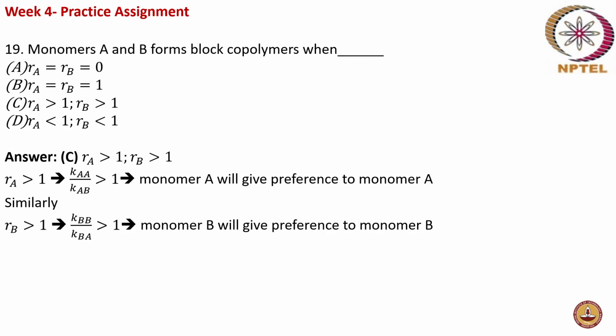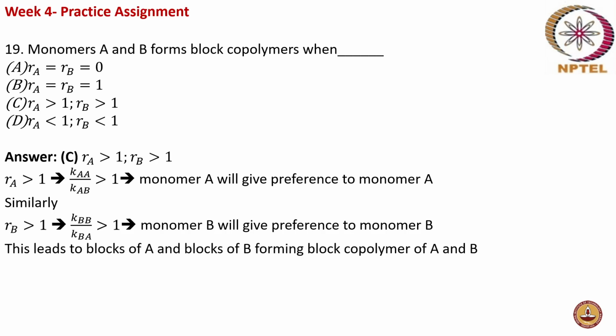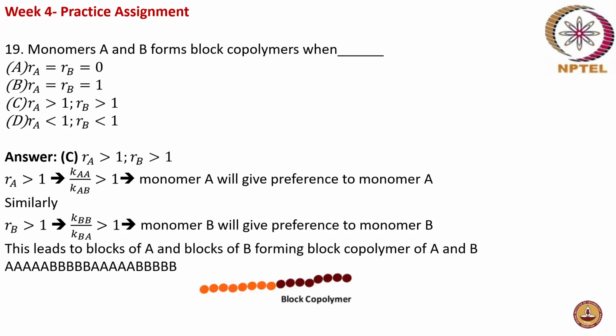And when will RA equal to RB be equal to 0? Then it will be alternating polymer, ma'am. Yes, that means A preferentially joins only with B and B preferentially joins with A, because your denominator should be higher. If the denominator value is very high, the fraction value tends to 0. That means you end up with the alternating copolymer. This is the explanation. The other case leads to a block copolymer of A and B, forming blocks of A and blocks of B. This is the block copolymer structure.